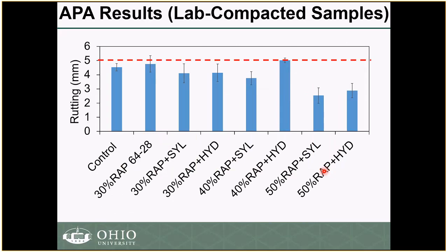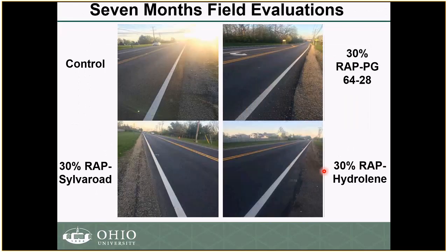In terms of the rutting, all mixtures really had a rutting that is less than the 5 millimeter. What you can see here also is that, except for that 40% RAP, all the RAP mixtures had lower rutting as compared to the control. But again, all of them met the criteria.